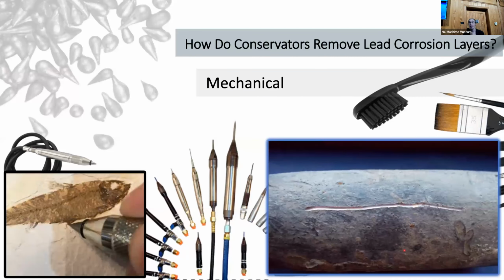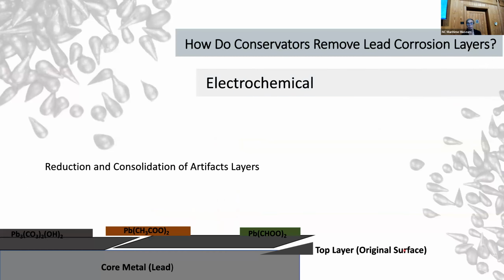However, of course, the biggest problem with mechanical cleaning is that lead is very soft. And in the course of your mechanical cleaning, you could accidentally, unintentionally damage the surface, add scratches and information that is not there, as well as actually destroy the thing that you're trying to uncover. So mechanical cleaning is used very, very sparingly with most types of lead, and we don't really rely on it to get those voluminous, crusty materials off the surface.